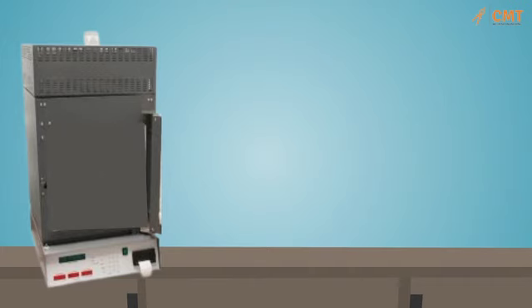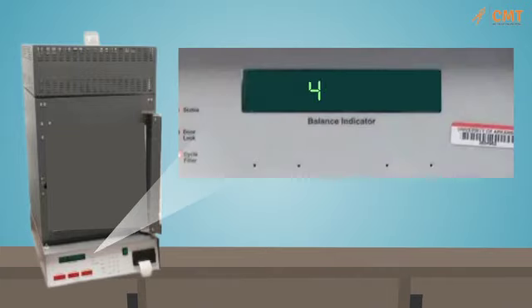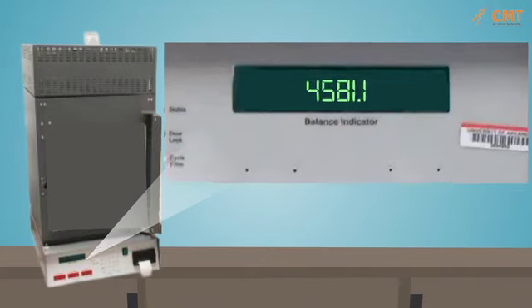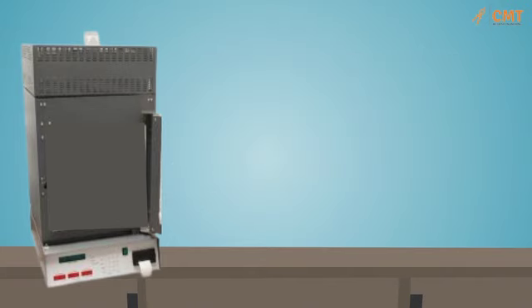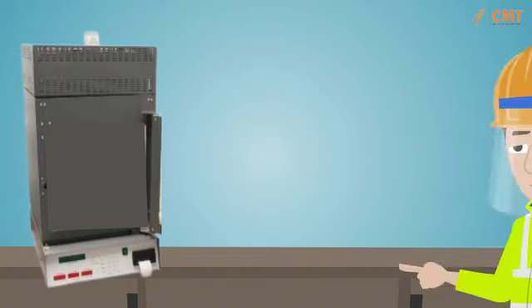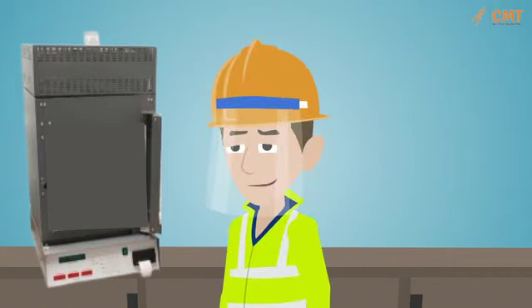Next, you will need to verify that the total mass of the basket assembly and sample shown on the oven display is within 5 grams of the total mass recorded from the external scale. If not, you will need to reposition the basket assembly to eliminate rubbing or check the scale calibration. Once the total mass is verified, you will need to start the ignition oven burn sequence by pressing the start button. The scale will zero out and the asphalt coatings will begin burning off the aggregate. The mass loss may be monitored on the oven display.